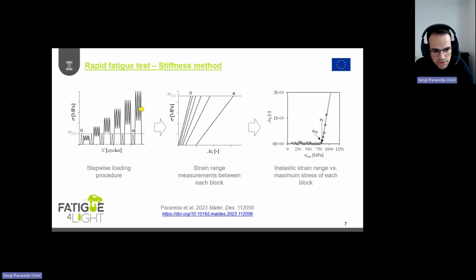And then we apply some fatigue cycles, and we measure once again the strain for this stress level. Then we increase the fatigue stress, and we apply more blocks. So at the end, until we reach the fracture of the specimen, we have this evolution of the strain for each one of these fatigue blocks.